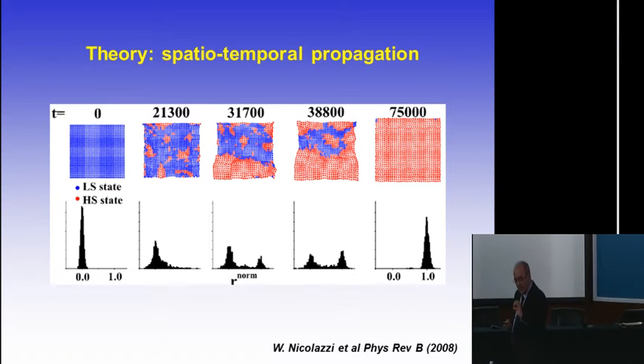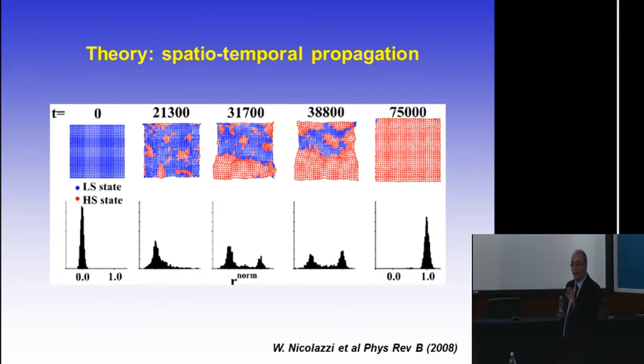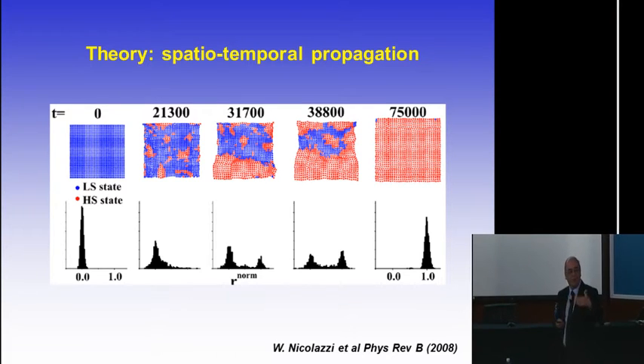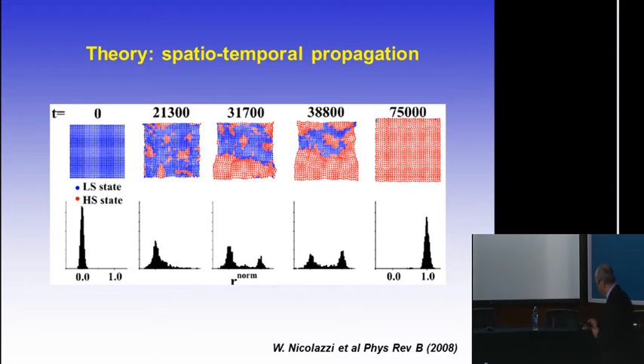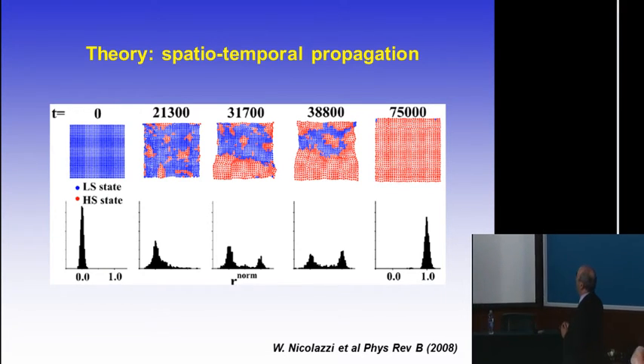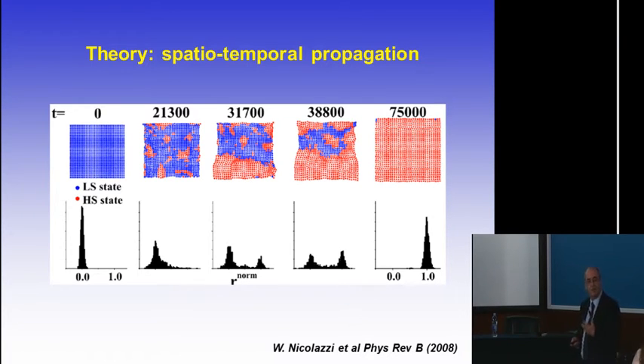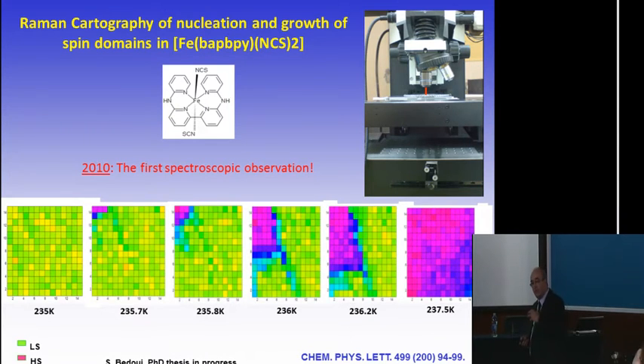That means that you have one place where you have the switching, and from neighbor to neighbor, through nucleation and growth, you have all the system converted. That was the question. So if we use the Ising-like model, as I showed you, and solve it through the crystal, what does the model tell us? The model tells us that when you go from the low spin to the high spin, you can go through a nucleation and growth process. Could we demonstrate that when we switch our system, we are going through nucleation and growth?